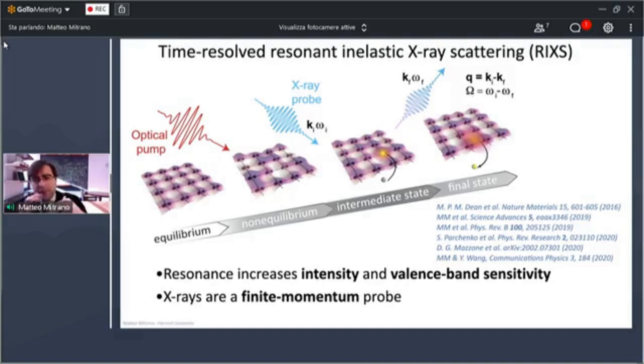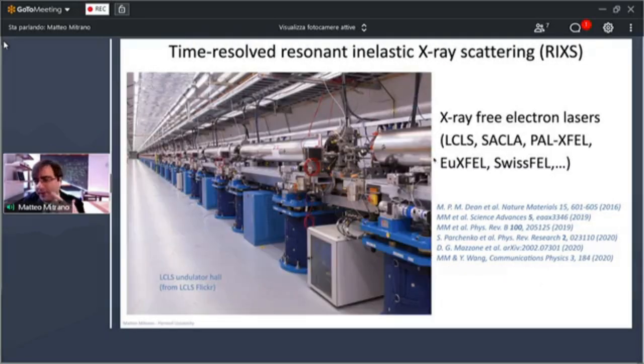And the fact that we can use X-rays is actually really important, because the fact that they are resonant to a certain atomic absorption gives you a boost in intensity that is much needed, but also valence band sensitivity. So you can really follow the dynamics of the low energy states close to the Fermi level that really contribute to the transport properties. In addition, using X-rays with high energy gives you the possibility of sampling properties at finite momentum. So you can really investigate the microscopic physics. The way we do this is by using particular accelerators that are so-called X-ray free electron lasers.